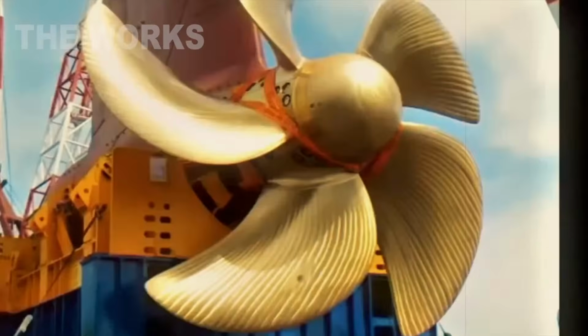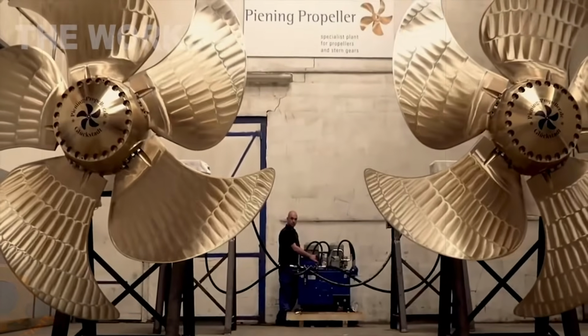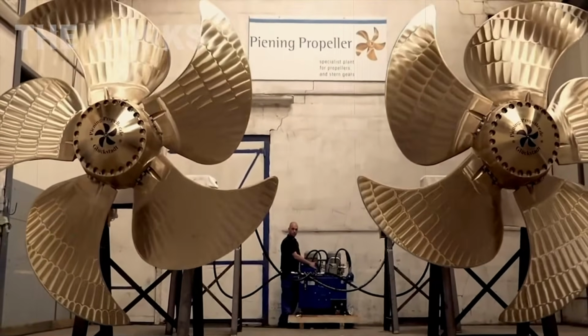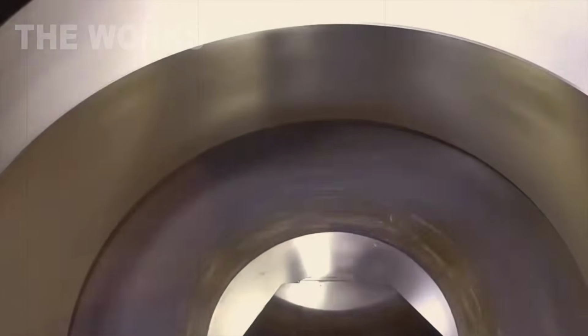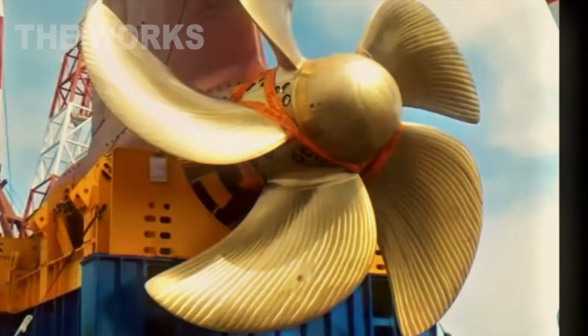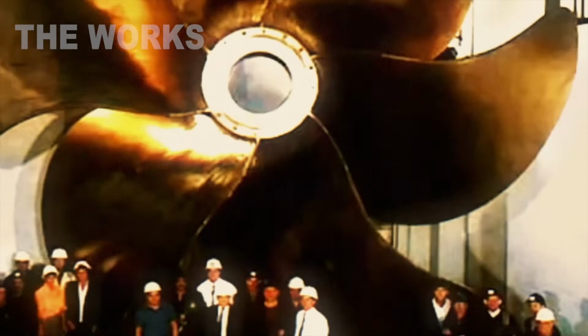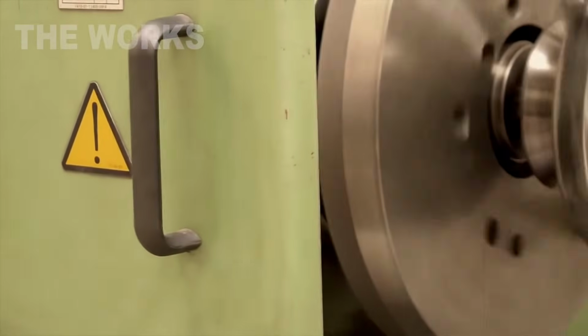The final operation, non-destructive testing. The propeller is X-rayed, checked with ultrasound, examined using magnetic particle inspection. They're looking for internal defects, voids, cracks, inclusions. If they find a critical defect, the propeller is scrapped. 287,000 pounds of metal and a month of work go to waste. The cost of such a propeller, $1 to $3 million.